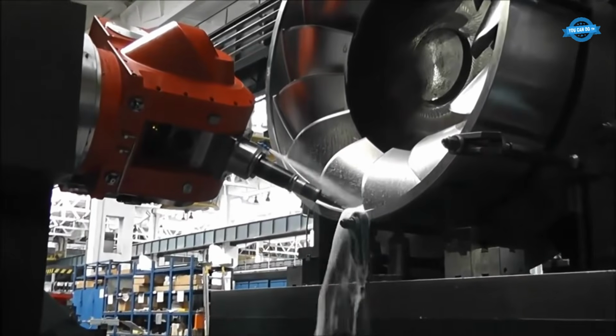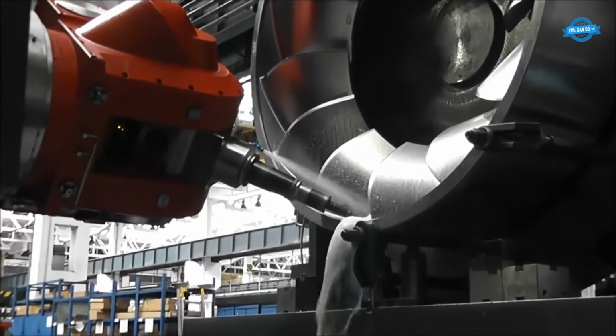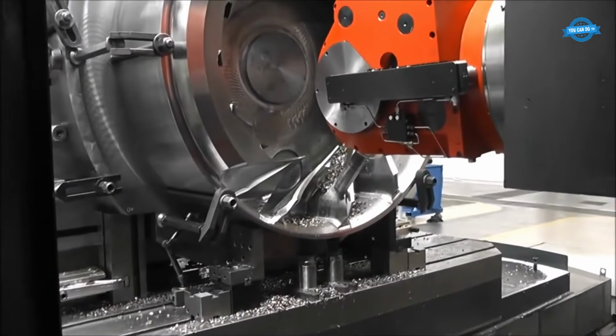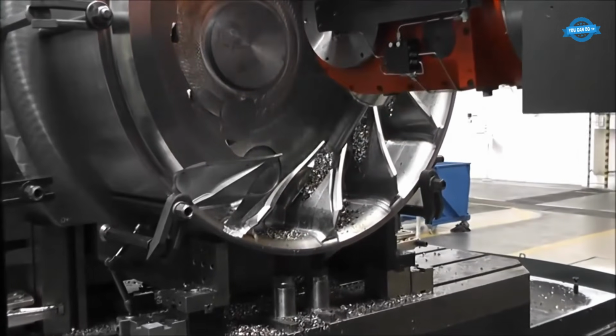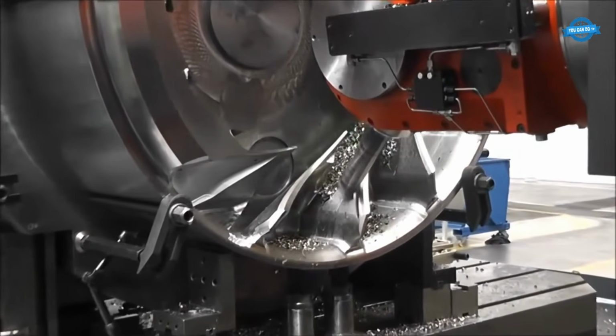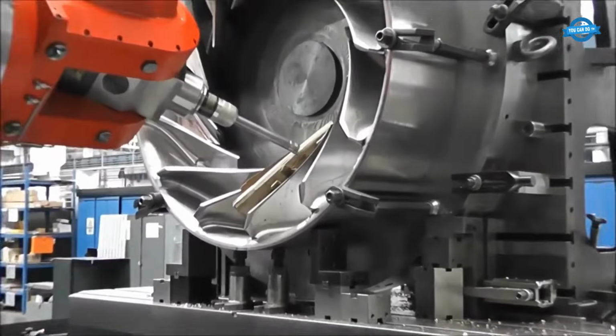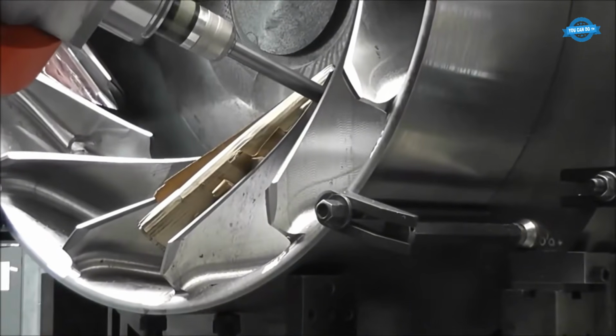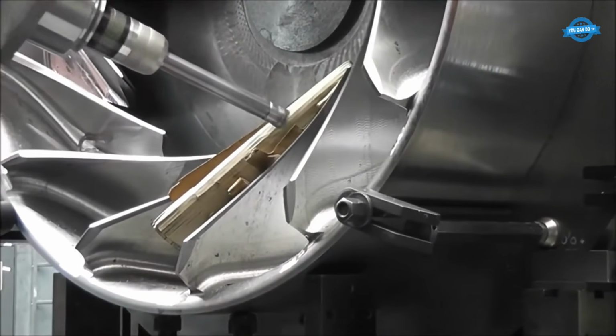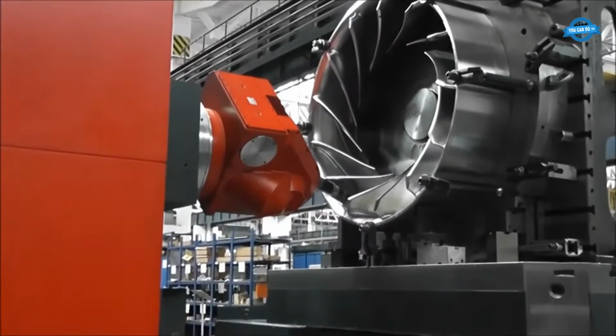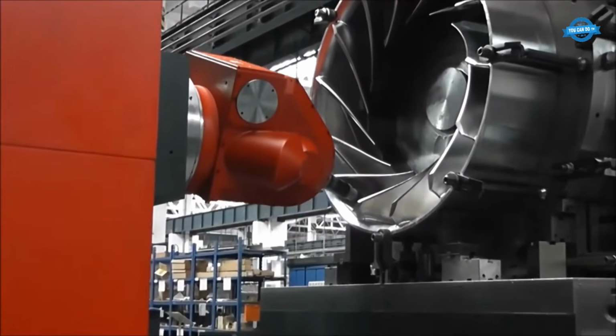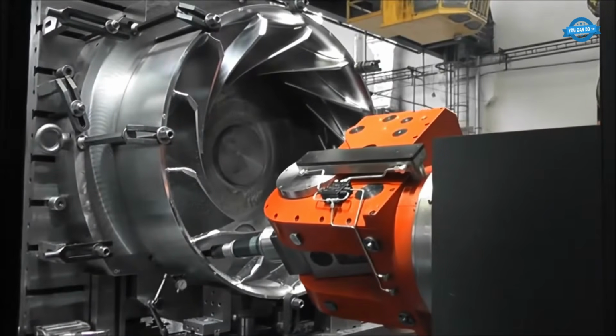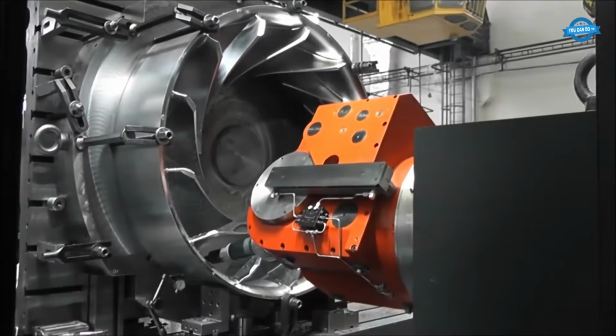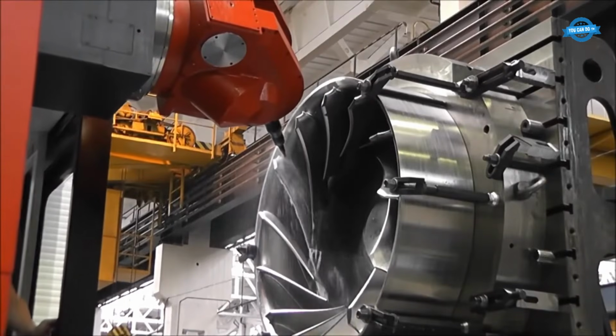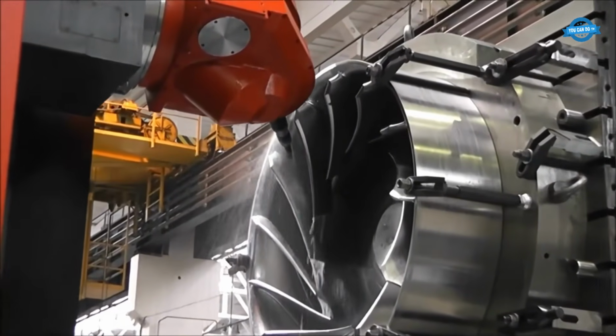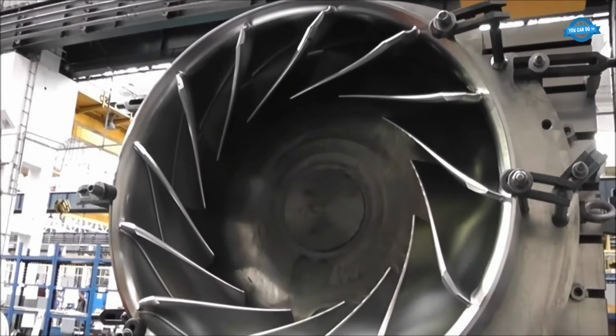The multi-axis setup is what makes the pocket geometry possible at all. A fixed axis mill couldn't reach in. Where the curve gets tight, the tool path slows down. Where the surface needs polish, the head switches to a finer tool. Coolant runs constant during the finishing pass. The finished turbine then spins true under its own balance, alignment proven by symmetry, not hope.